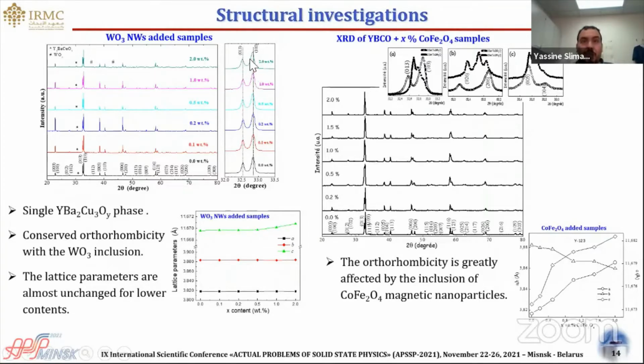Also, no noticeable shift in XRD peaks, as well as no noticeable variations in the lattice parameters. This indicates that the orthorhombicity of the material added with tungsten oxide nanostructured materials was conserved with the addition of small and appropriate amounts of tungsten oxide nanostructural entity.